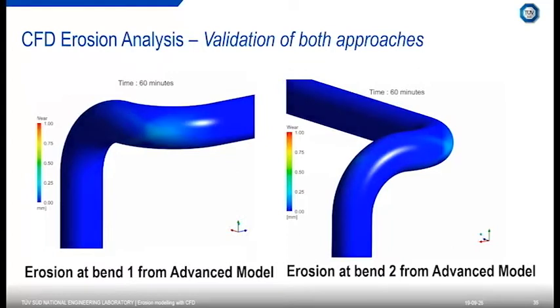because if that is not an accurate representation of what's actually happening with these particles, you may predict the erosion on the first part quite well, but on later elements of your system you may be predicting the wrong regions. And that's really important when you're starting to change the geometry as well, because you could get completely erroneous results further downstream.